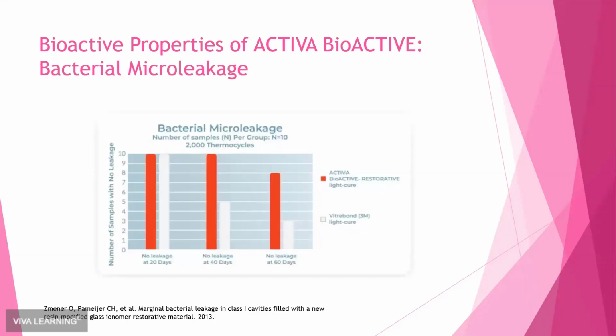And then if you have less marginal microleakage, it's probably not surprising that you're also going to have less bacterial microleakage. So here we are looking at the number of samples that had no leakage after a period of time. The red, the left bar on the graph, is the Activa, and the right is Vitrabond. At 20 days, the amount of samples that had no leakage for each material was the same. But you can see that at 40 and 60 days, the Activa is outperforming by having a higher amount of samples with no leakage.